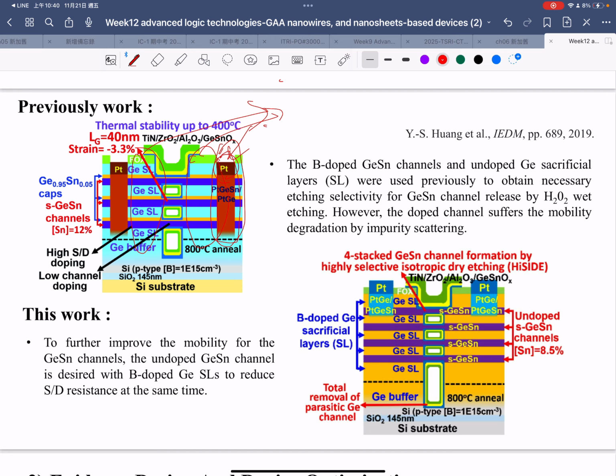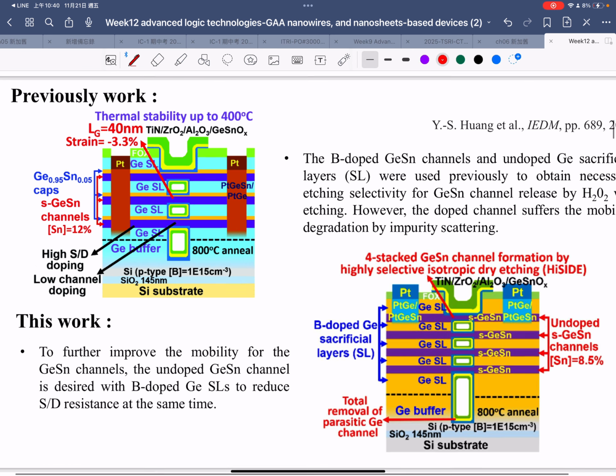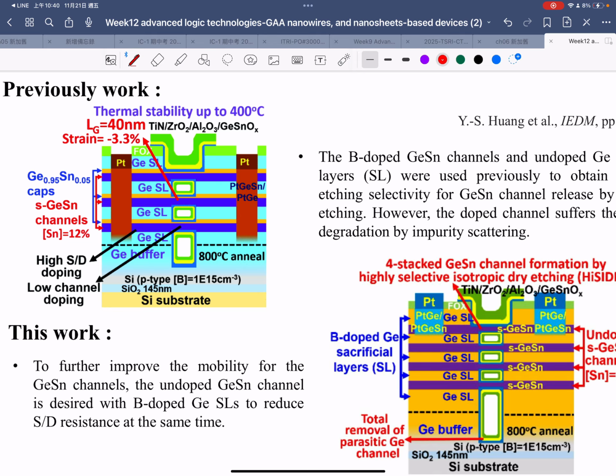Okay, because we still have to suffer high resistance in the area. Okay, and then this is their layer. They use the germanium tin cap, and then they have a high-strain germanium tin channel, and the concentration is about 12%. 12% is a very high concentration.